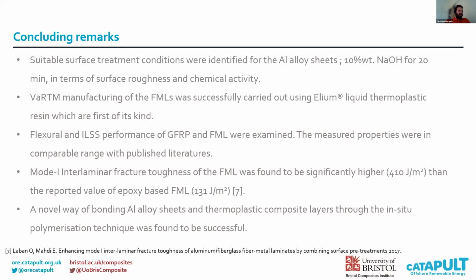Here are some concluding remarks from this study. Suitable surface treatment conditions were identified for these aluminum alloys, in terms of surface roughness and chemical activity. Manufacturing of the FML was successfully carried out using thermoplastic resin, which is the first of its kind. Flexural and interlaminar shear performance of the GFRPs and the FMLs were examined, and the measured properties were in a comparable range with the published literature.